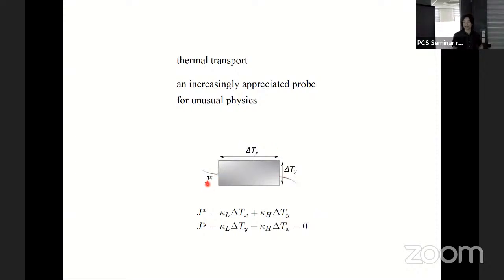So this Jx can be understood as some heat current. The heat current only runs in the x direction, and then you measure the temperature drop in both the x direction and y direction. Then you have the longitudinal coefficient, which is the longitudinal thermal conductivity, and the transverse coefficient, which is the thermal Hall conductivity. In particular, because in the experiment the power is only being sourced and drained in the x direction, in the y direction the current is 0. But overall, from these measurements, you can determine the values of kappa_L and kappa_H. So this is a thermal transport experiment.